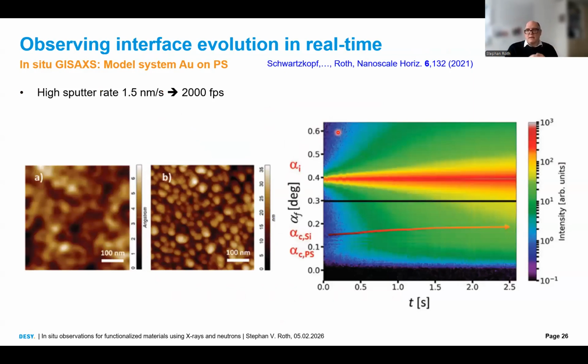You see here quite some time later, because this took into account the advances in synchrotron radiation from second to third generation and advances also in data analysis. So what we did here, we used a very high sputter rate, 1.5 nanometer per second. The other experiments I have shown you up to then were 0.1 nanometer per second, 0.2 and so on. And when we told this to industry, they said, you're much too slow. So we said, okay, we can do better. And we managed 1.5 nanometer per second, which is still the record in in situ deposition with GISAXS.